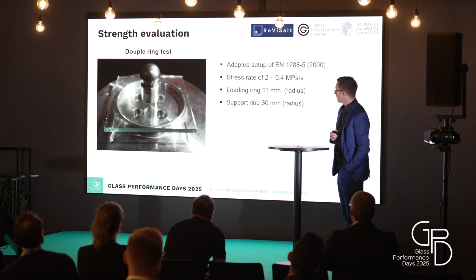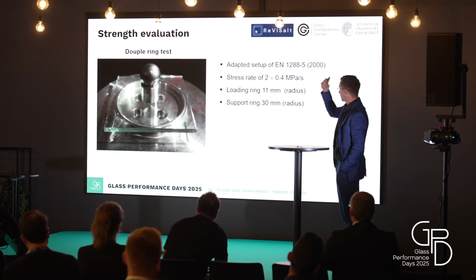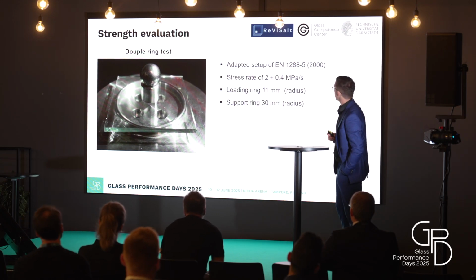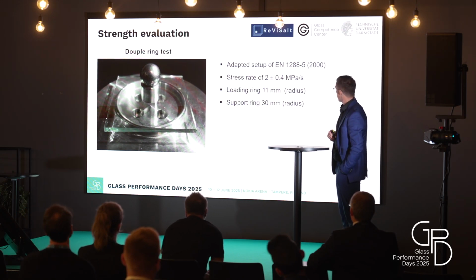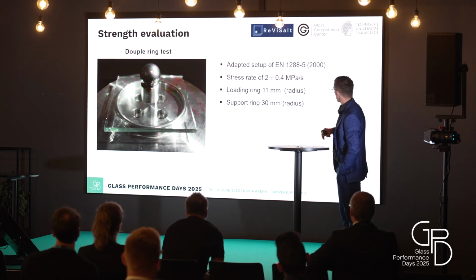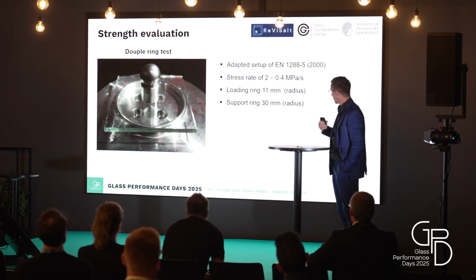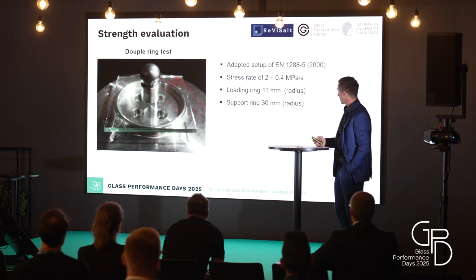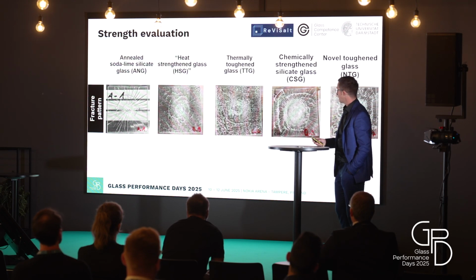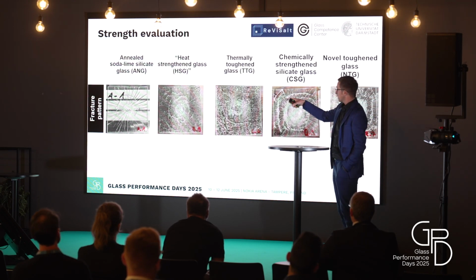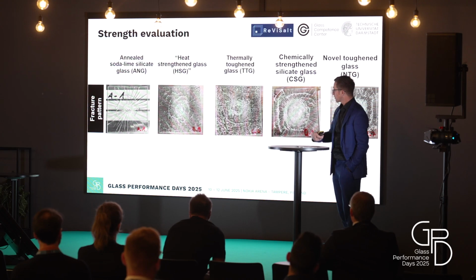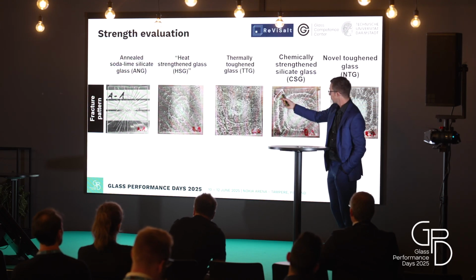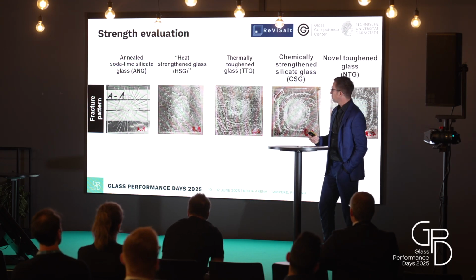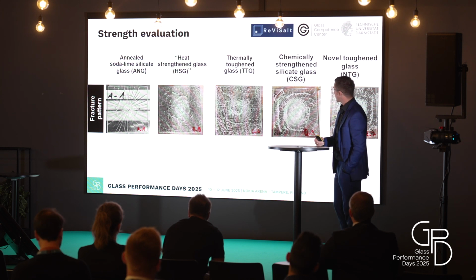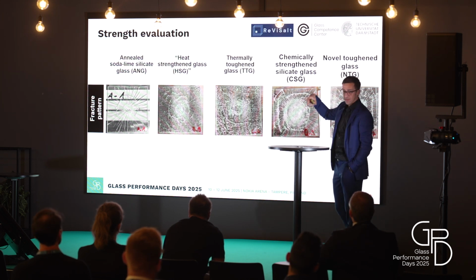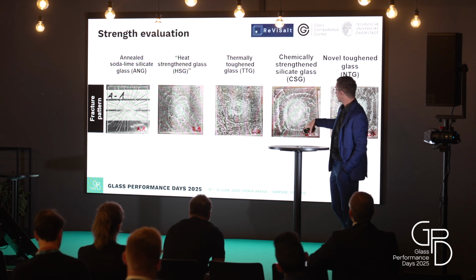Okay, fracture pattern as an anisotropic thing. We also conduct a double ring bending test. Sorry for the miswriting there. We do a typical double ring bending test with adapted load ring and support ring for this glass, and I want to come to the results. These are the fracture patterns. On the left side you see the fracture pattern for normal annealed glass. This is typical. We see also here the fracture pattern for heat strengthened and fully or thermally toughened glass.